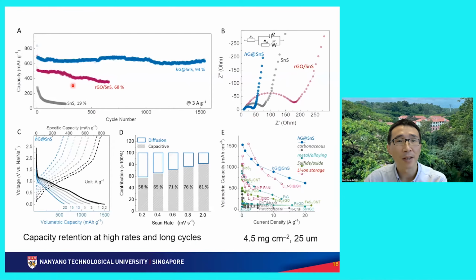So indeed, if you take the pure tin monosulfide, the capacity retention is less than 20%, at about 250 cycles. So in less than 50 cycles, the battery fails. If you physically mix with RGO, you get about 70% capacity retention after less than 600 cycles. But our design can extend to 1,500 cycles. Okay? This is a detailed mechanism that we will not go into.